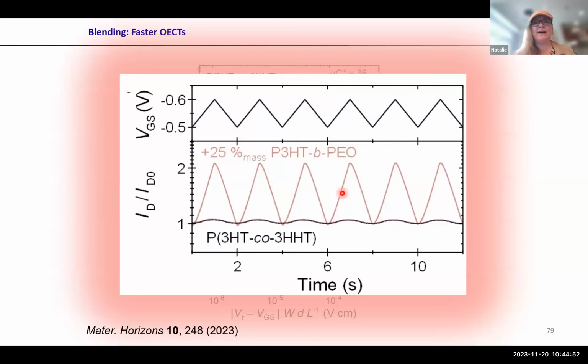But just to show graphically how the speed changes. So if you now have the OECT and you change the gate bias voltage from -0.5 to -0.6 over time, if you only have the neat material, you see the device is far too slow to follow the gate bias. However, once we add the block copolymer, and again, I'm sure we can get even better, the source-drain current really follows nicely the gate bias we apply.